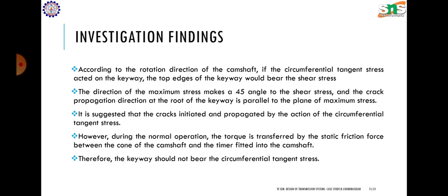So the crack propagation direction at the root of the keyway is parallel to the plane of the maximum stress. So it is suggested that the cracks initiated and propagated by the action of the circumferential tangential stress. So this circumferential tangential stress may cause the crack initiation and propagation.